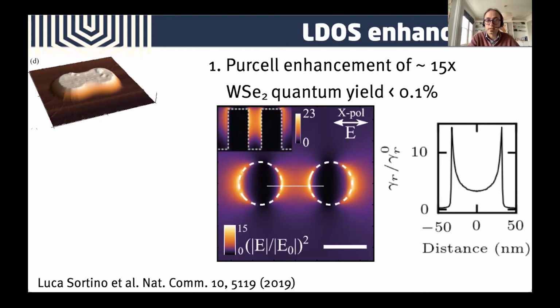Now, this is very important because not only are we increasing the decay rate, but we are also boosting the quantum yield of the material, because the quantum yield is very low. And so we have a much larger quantum yield because we are enhancing the optical processes with respect to the non-radiative processes. You see here that it's not homogeneous everywhere. There is a much higher enhancement very close to the antenna, but on the other hand, it's fairly flat in the middle. And so overall, we have a 15 times enhancement.